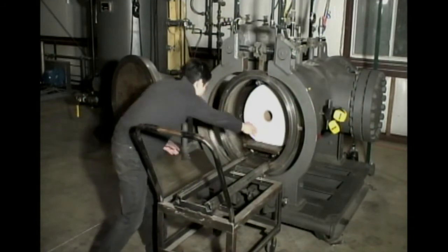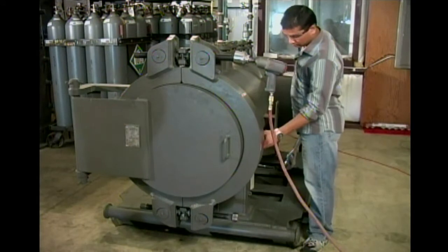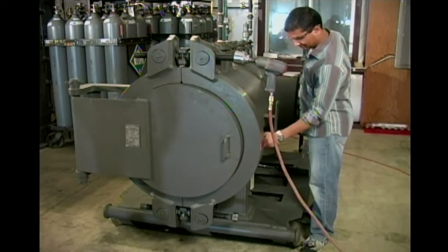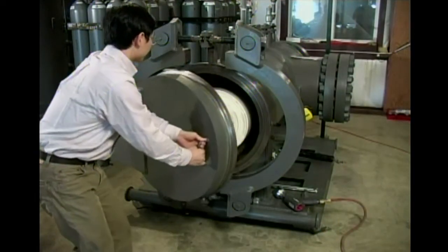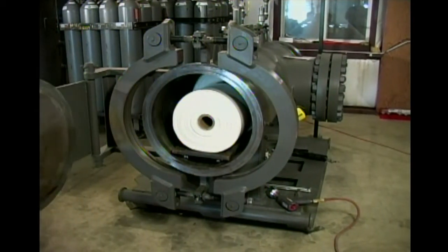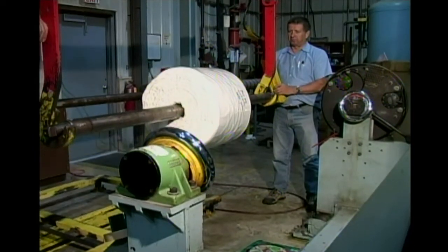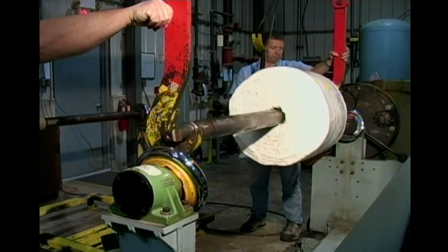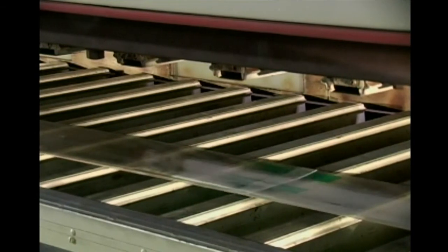First, the polymer is loaded into a pressure vessel. Next, the polymer is saturated with food-grade carbon dioxide in the pressure vessel for an amount of time appropriate to the application, and then removed from the vessel. The carbon dioxide is now trapped between the polymer molecules and still under pressure. The interleaved and saturated roll is mounted on an unwind stand from which the polymer will be fed through a heated air flotation oven. The saturated roll is connected to a leader,